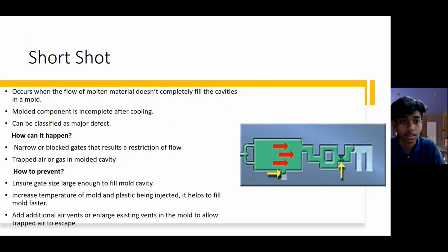So for the last defect, we have short shot. Short shot may occur when the flow of molten material doesn't completely fill the cavities in the mold. The molded component is incomplete after cooling, and short shot can be classified as a major defect. How can it happen? First, narrow or blocked gates that result in a restriction of flow. Second, trapped air or gas in the mold cavity.